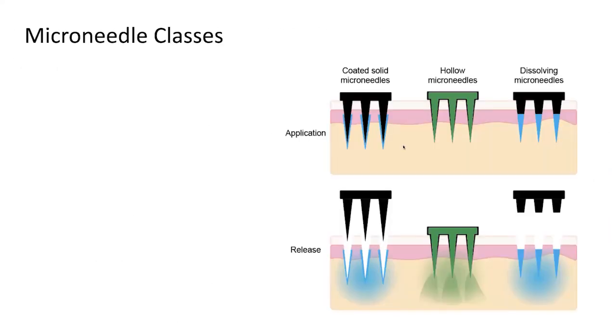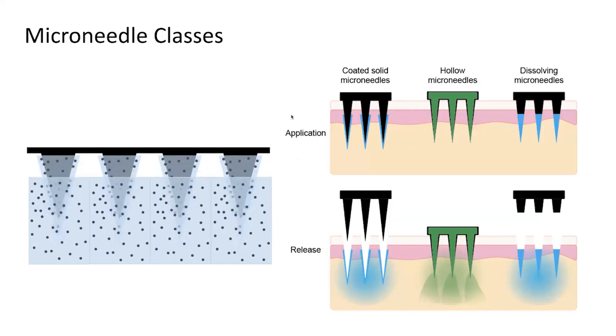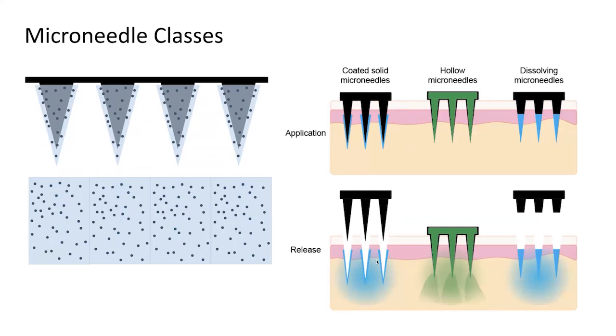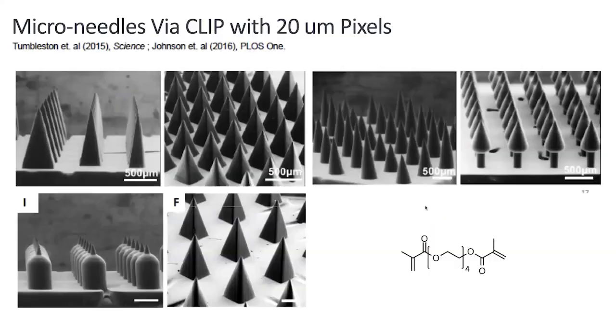If you look at the different classes of microneedles, they come in at least three buckets. One would be a solid microneedle that you'd want to dip coat into a liquid or coat somehow, and then you inject those needles into the skin and just leave the coating. Probably from a regulatory point of view, this is the lowest regulatory hurdle, because you're using it almost as a needle temporarily. The needles are not left in the skin, it's just the coatings. Hollow microneedles are also like a syringe, leaving the liquid in the skin and pulling the needle out. And then there are molded or 3D printed microneedles that are not designed to be removed, but instead lodge in the skin. They can give new opportunities too, and will have a higher regulatory hurdle than these.